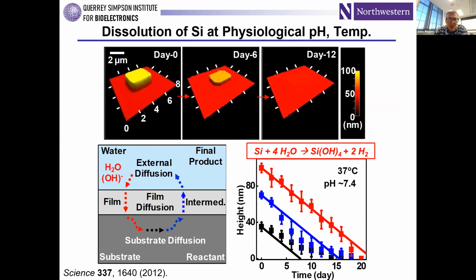But what turned out to be the case, and we just stumbled across this, is that if you take those nanostructured sheets and ribbons of silicon, and if you're careful with what you're doing and observant in the lab, what you realize is that they themselves will dissolve away in water. And so what's shown here are atomic force micrographs, with magnified z-axis on these images, showing the gradual dissolution of a nanoscale platelet of monocrystalline device grade silicon when immersed in a phosphate buffered saline solution at physiological pH and temperature. And what you find is through reactions that involve surface erosion, the silicon will just gradually dissolve over the time scale of a couple of weeks.